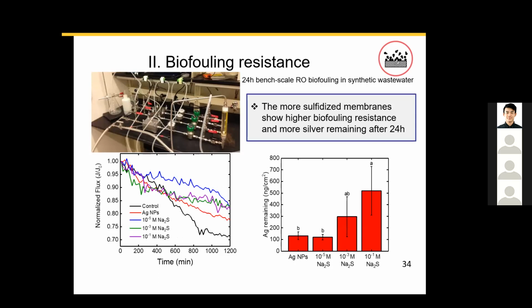The next thing that we wanted to see is, because we know that silver is an antibacterial, whether we can apply this in a reverse osmosis bench scale system to reduce biofilm formation. We operated this system for about 24 hours. We loaded the membranes into each of these chambers, and we saw that the unfunctionalized membrane was the first one to decrease in flux. We attribute that to the formation of biofilms on the membrane surface. But if we test the sulfidized particles, we see that the flux is still pretty good, and it takes longer for the membrane flux to decrease.